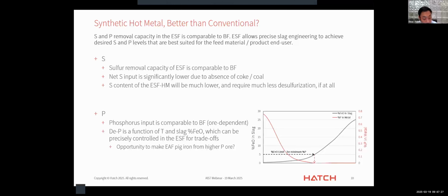A little bit more on the sulfur and phosphorus side of things. Again, the sulfur removal capacity of the ESF is comparable to the BF in general, depending, of course, on precise slag engineering. The net input of sulfur is significantly lower. Therefore, we expect the sulfur content of the hot metal to be significantly lower than that from the blast furnace.